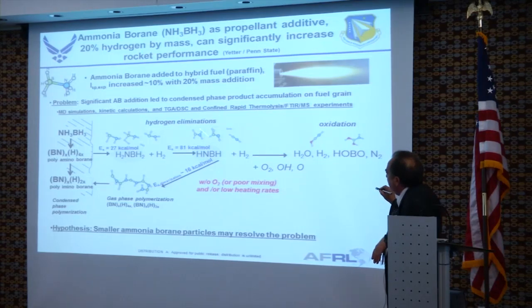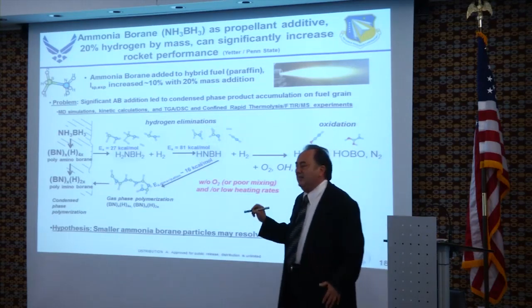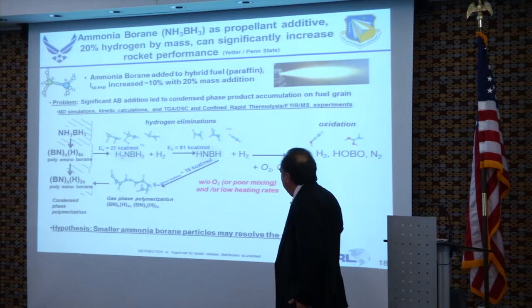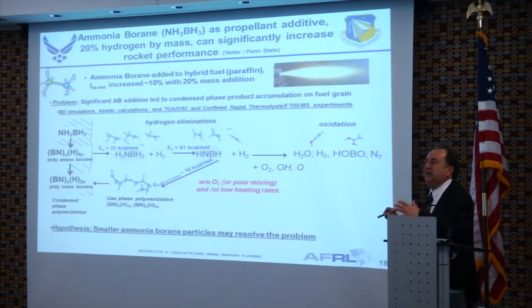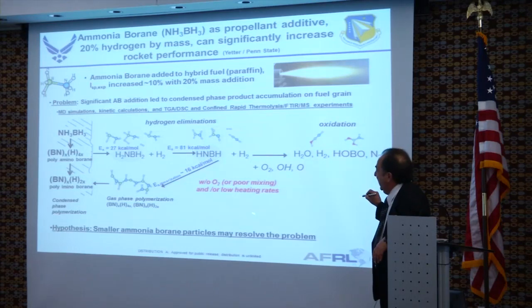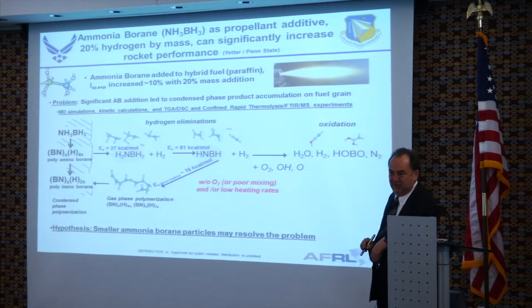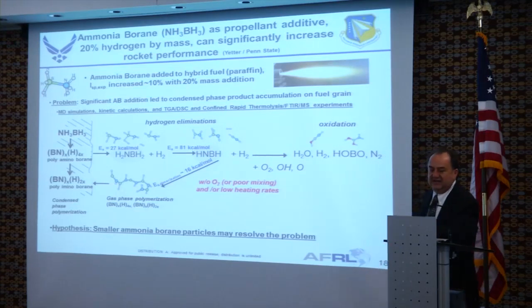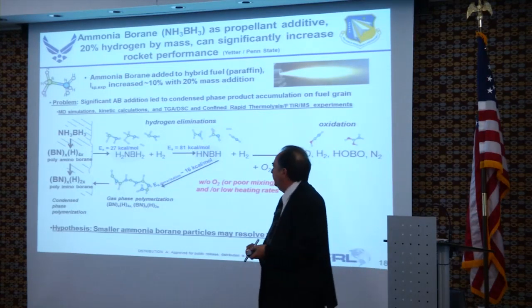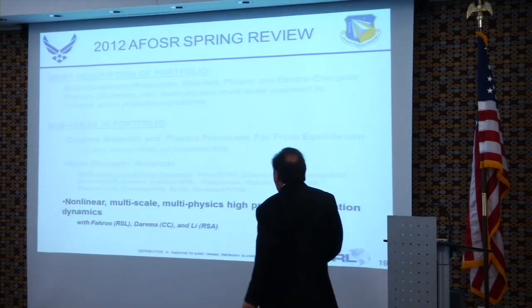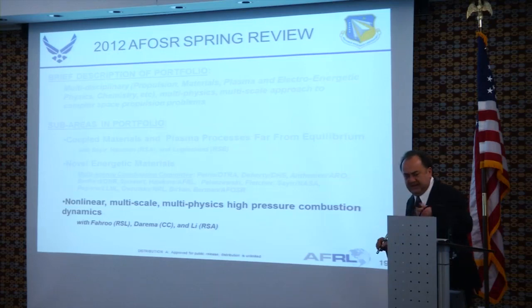There are two hydrogen elimination reactions, but look at the activation energies for the two hydrogen eliminations, and then the oxidation. But there is a polymerization possibility which has a much lower activation energy. So if there is no oxygen or a low heating rate, or if we can use smaller particles, they can heat faster and finish that business of the ammonia borane burning without creating a crust. Okay. Third area, nonlinear multiscale multiphysics stuff.